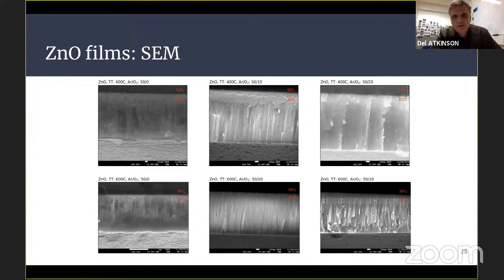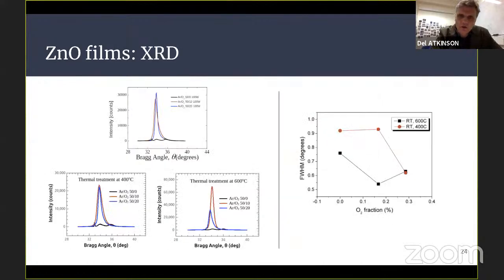So can you go back to the previous screen with the XRD? There are a couple of things I want to ask you. Firstly, if we look at the graph on the right, if you're increasing the oxygen concentration of the gas during the deposition, would you expect to change the oxygen content of your film? Yes, we were expecting that. So is that what's happened? Is the oxygen going interstitial? Where's that oxygen going? Was it lacking oxygen and then you brought it up to a stoichiometric value, or are you now pumping oxygen in and distorting the lattice? Do you have any idea?